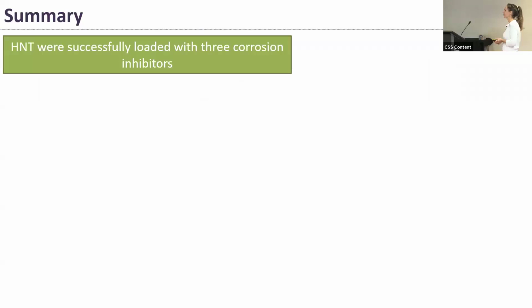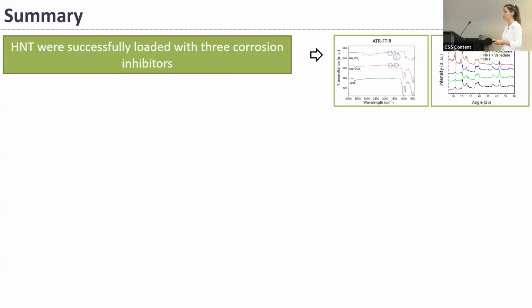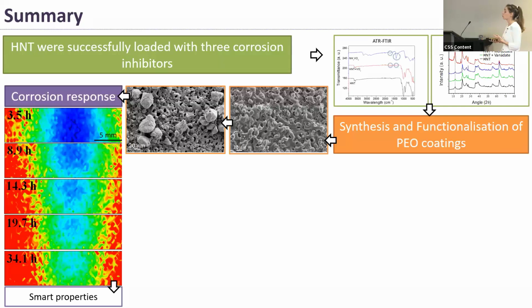So let's finish with a brief summary. In this work, we successfully encapsulated 3 different corrosion inhibitors into halloysite nanotubes. We characterized them by infrared spectroscopy and by XRD to figure out the location of the inhibitors within the nanotube. We synthesized the coating and functionalized it. We tried a single-step process, which wasn't very successful, but we did manage to obtain some self-healing properties using a 2-step process.